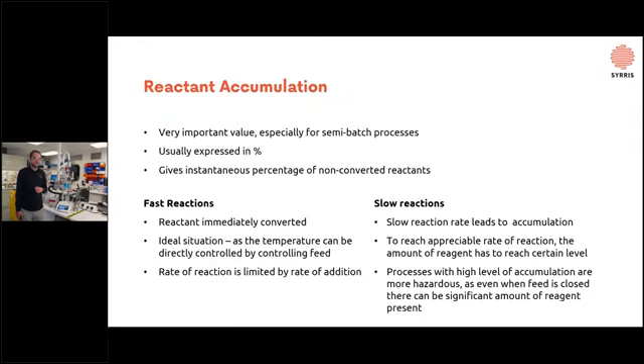And the last very important one is reactant accumulation, because in percent, it gives us the instantaneous percentage of non-converted reactants. So we have two scenarios, fast and slow reactions. Fast reactions are usually very desirable because, for example, if we dose some reagent inside a reactor, it would immediately react and we have an immediate response from the reacting system. So we can control the rate of heating by limiting the feed rate of the reagent. But that's unfortunately not always the case, because if we encounter slow reactions and we add too fast, we will have unreacted reagents inside the vessel. We literally have no control. We can't really do anything while it's inside.